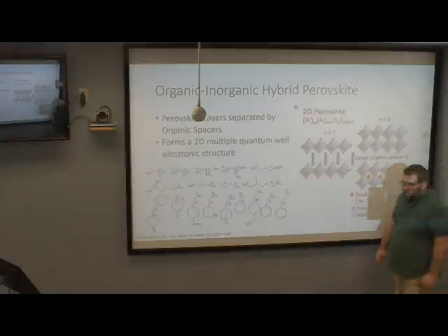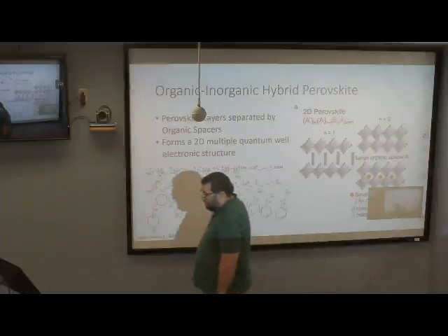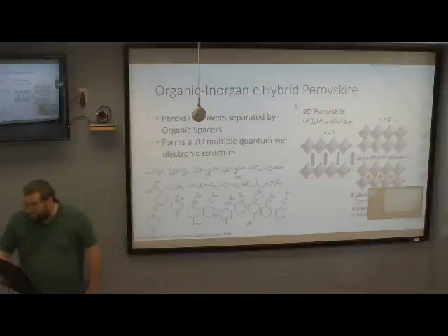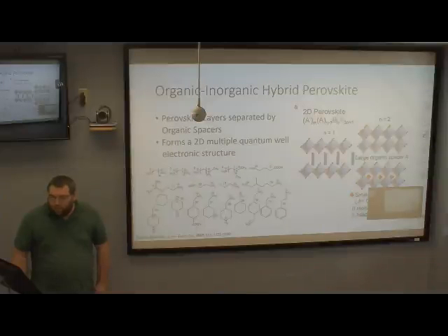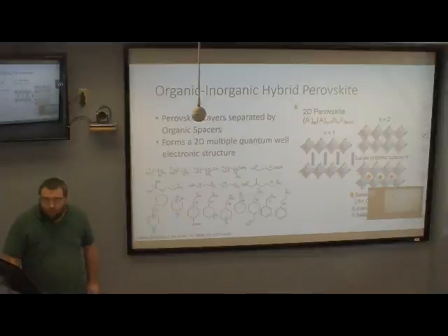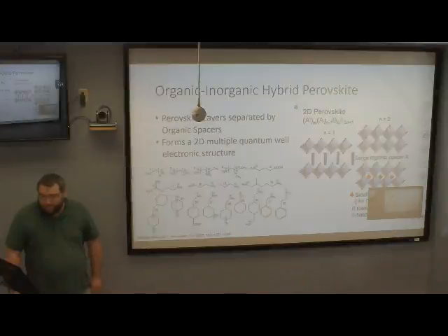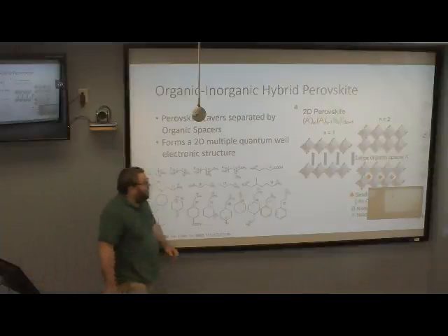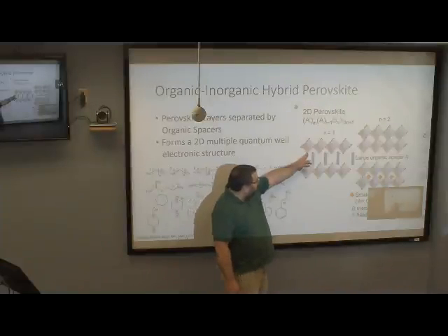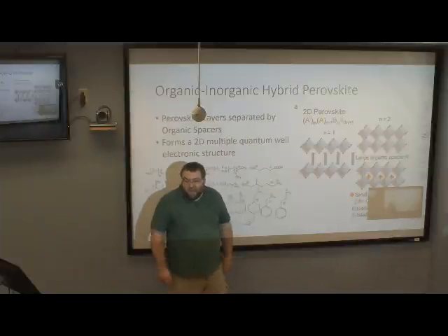Mechanism of binding. There is no doubt that you understand it, but it's better to verbalize it, speak it slowly. Why does the ammonium group bind to the surface? What does it do to the surface? In these models, these red atoms are going to be halides, so they're an anion, and they ionically bond to the cation that is ammonium.